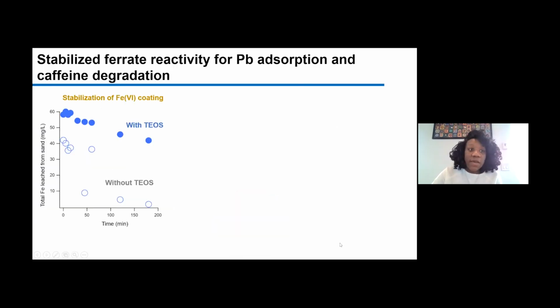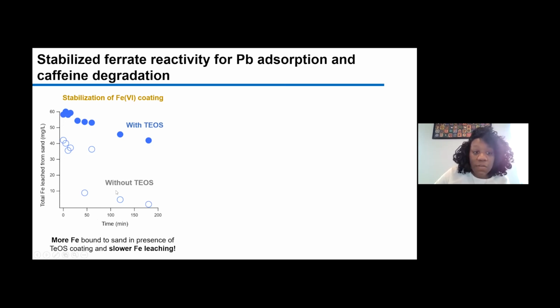Okay, so some preliminary data from this material. We were interested in testing it with lead and caffeine as representative organic and inorganic contaminants in stormwater runoff. But first, I mentioned that the TEOS binding was really essential for us, and this is the proof of that. So here we have time on the x-axis and then the total iron leached from the sand with and without the TEOS coating. So clearly with the TEOS coating, not only do we have more ferrate that's bound to the sand surface, but it's also stable for longer periods of time.